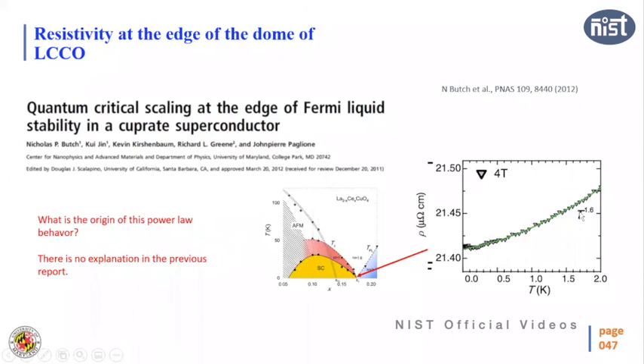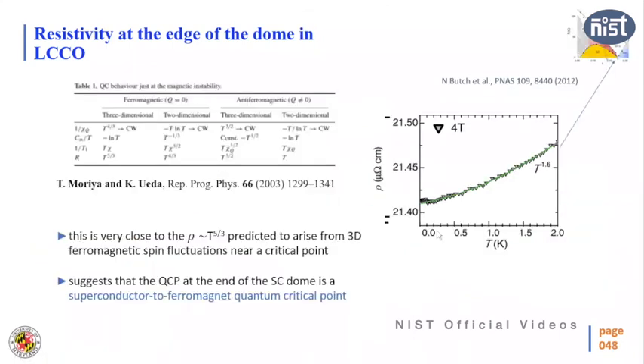And it also shows some kind of scaling behavior. From that scaling behavior, it was confirmed that there is some sort of criticality going on at the end of the superconducting dome. Now, if we assume there is ferromagnetism, then this power law, because it's very close to 5/3, could be due to ferromagnetic quantum fluctuations. So all this data suggests this could be the reason, because some theoretical papers predicted that if there is a ferromagnetic quantum fluctuation, the power law of the resistivity as a function of temperature should be 5/3.